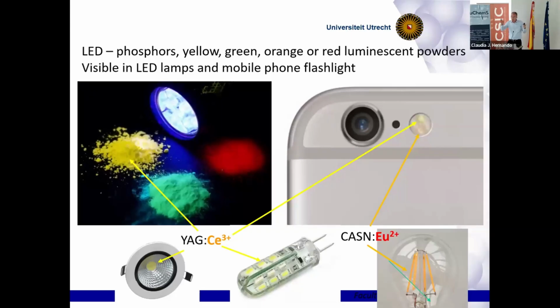To make it more warm white, you add red emitting phosphors like calcium aluminum silicon nitride doped with europium 2+. Again, a lanthanide. And here you see some of the phosphors under UV radiation.